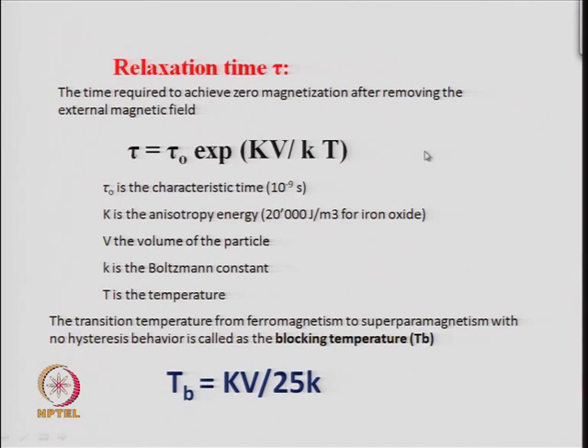So, this gives you the equation between relaxation time and the material property, which is the anisotropy energy, which is different for different materials, and for a very good magnet like iron oxide, that value is very high, is nearly 20,000, and of course, this will vary whether it is Fe2O3, Fe3O4 or iron metal, etcetera.